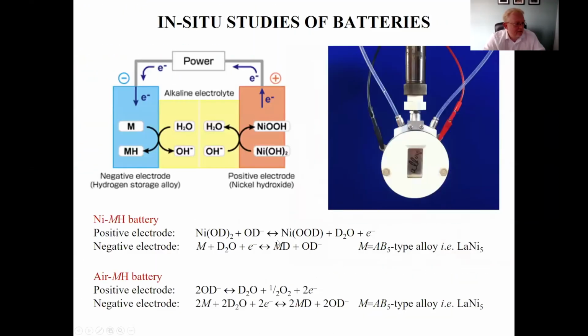The next question is, how do you maintain the liquid electrolytes during in situ battery characterizations? So for this particular cell, as you can see, we have pipe work to maintain the electrolyte, so we can actually pump out the electrolyte and pump it back in again, in situ in this experiment. So as long as these links here are gas tight, then we can easily change the electrolyte material.